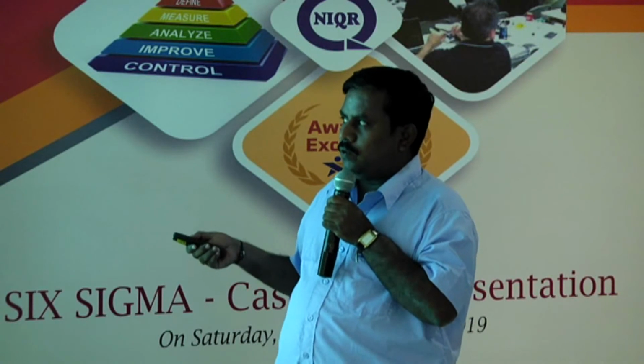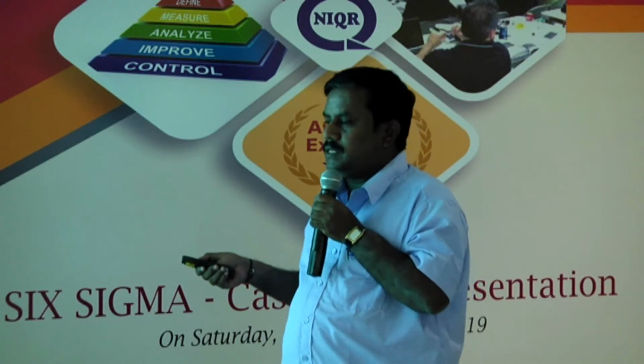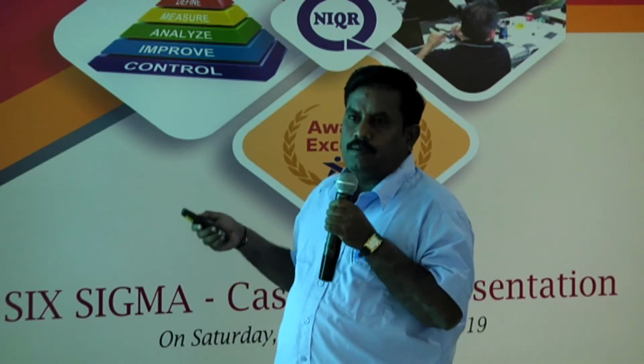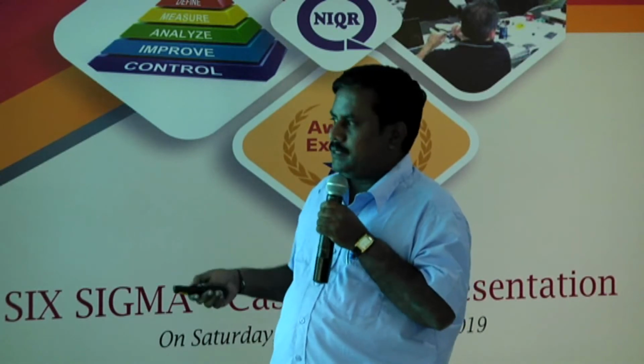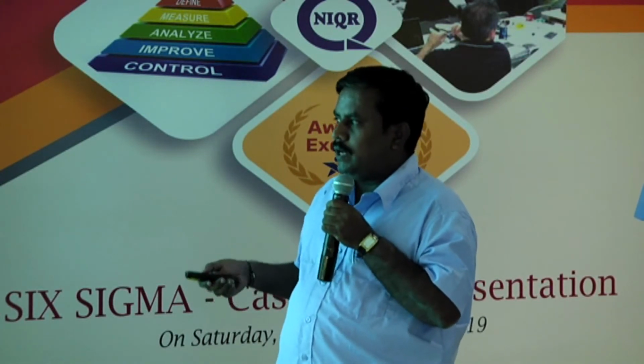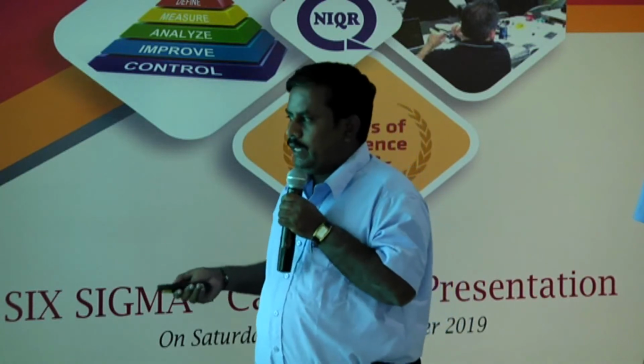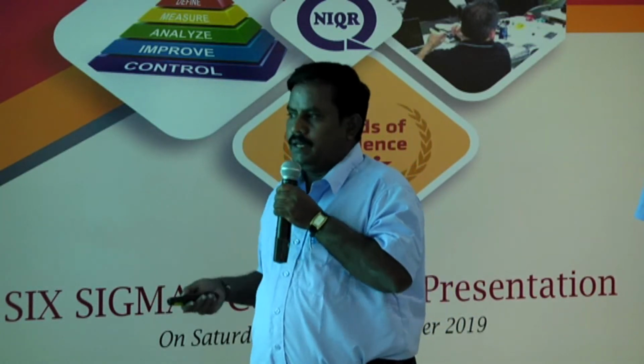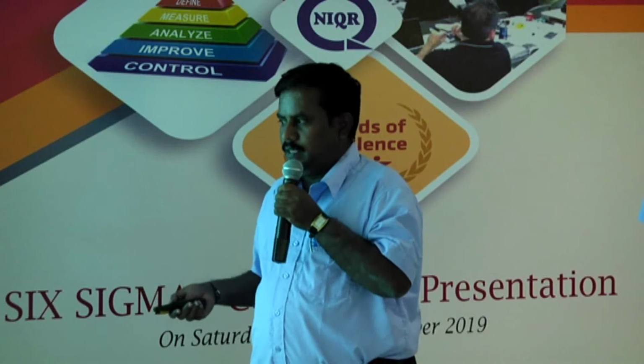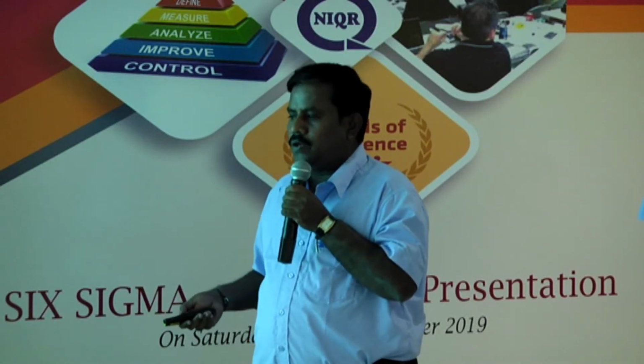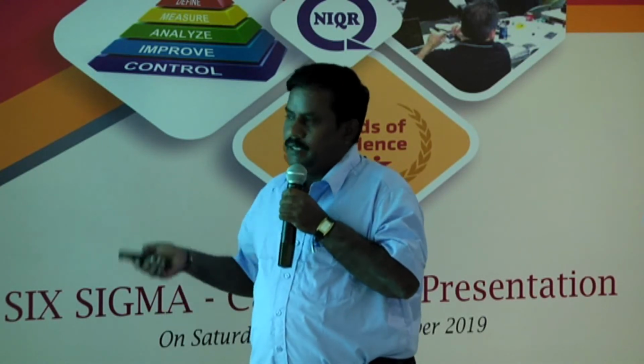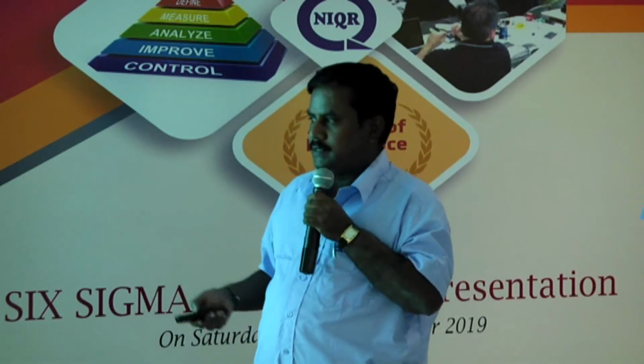Better condition is water cooling, introducing an additional vent, and die temperature with a revised specification of optimal parameters. And the current condition is without water cooling and no additional vent, and die temperature at 250 degrees. Sample size is 3B and 3C batches, and lot quantity is 500 numbers each batch, around 6 batches.